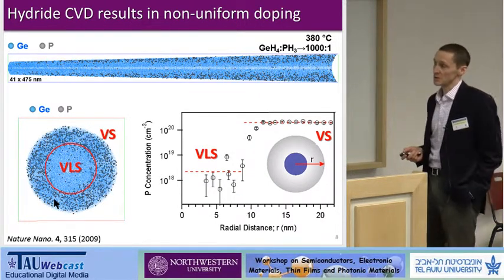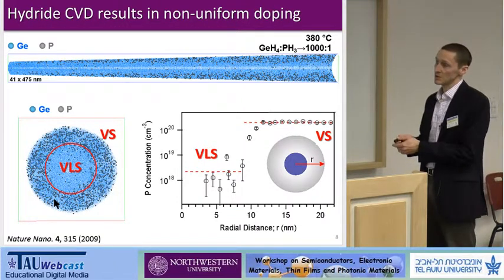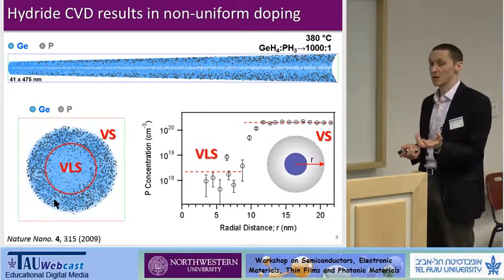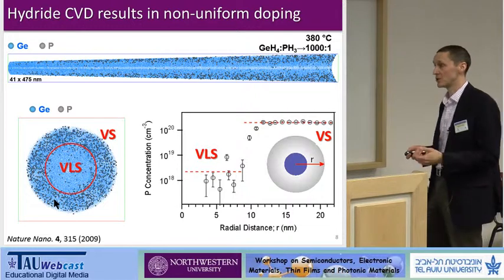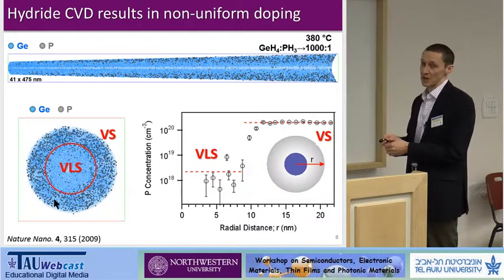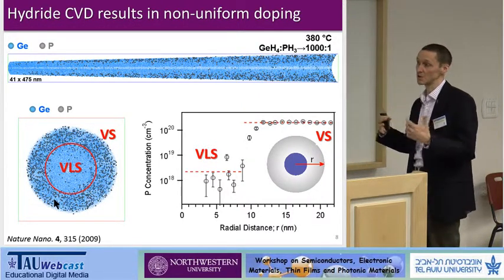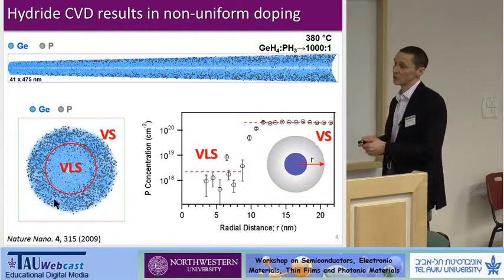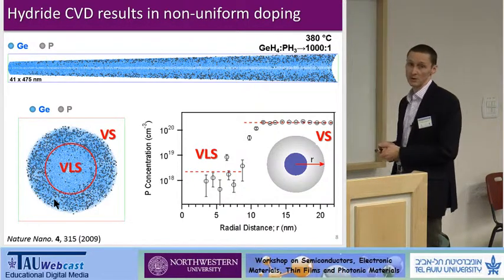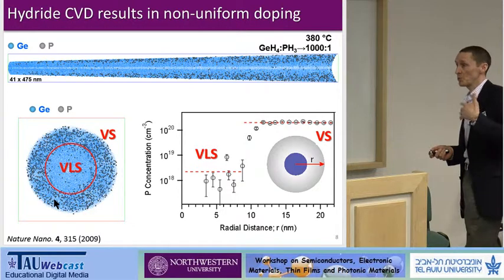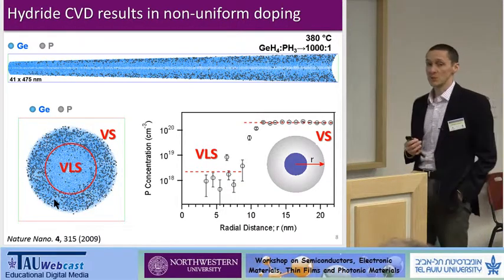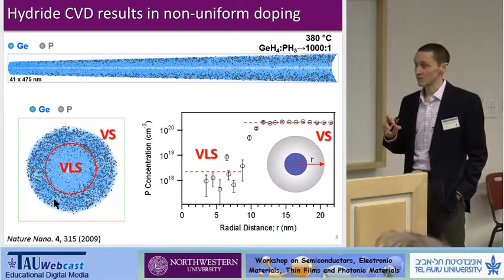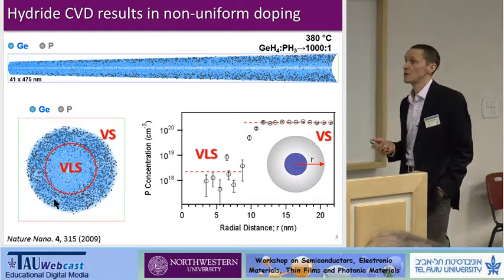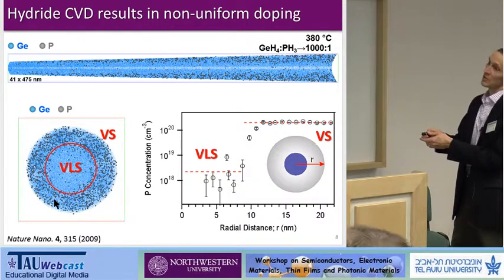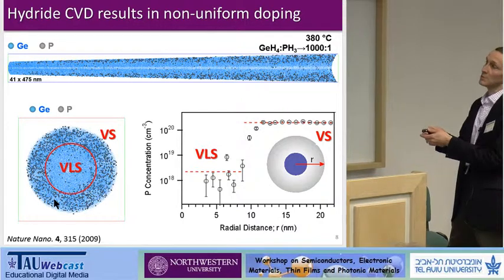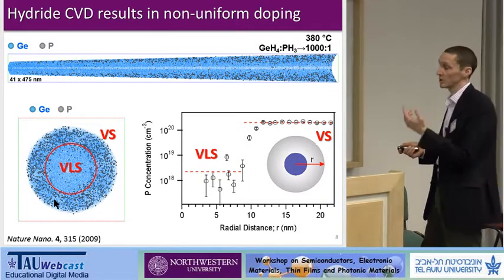And what we learned from these experiments was essentially that this VLS portion that was precipitating out of the gold was not as heavily doped as what we call this vapor-solid region, essentially the deposition on the side, which is much more highly doped by a factor of 2 orders of magnitude here. Okay? So the atom probe enabled us to understand something about the dopant incorporation kinetics that differed between these 2 different processes. And that's important because you can see if I go from one end to the other end of the nanowire, it's becoming more doped, so more conductive.